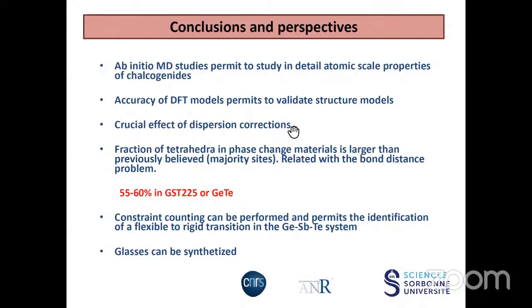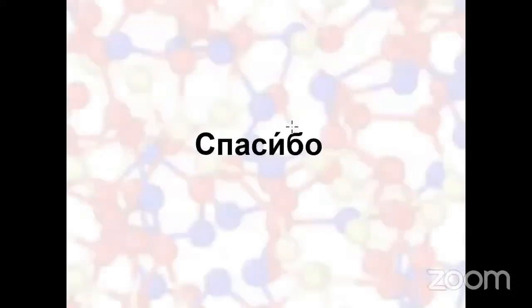And furthermore, I have tried to convince you that if you calculate the fraction of tetrahedra in a very rigorous way, that is not relying on angles, but on angular excursions, we realize that the fraction of tetrahedra is very large in those phase change materials. So this contradicts previous findings from ab initio simulations, but which were working without the Grimme corrections, so which basically were exhibiting this bond distance problem, this overestimation of GeTe bond distances. And finally, having in hand all these trajectories and tools, we have been applying a constraint counting algorithm to identify a possible flexible to rigid transition in this GST system. And so this might open also an avenue for exploring the glass forming tendency of this GST system, starting from this isostatic composition that we have identified. So, I thank you very much for your attention.